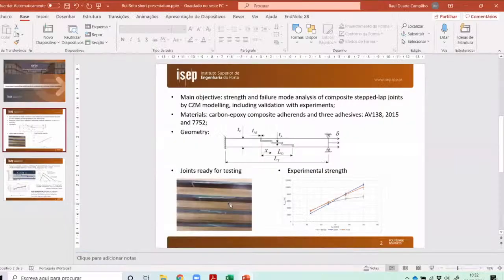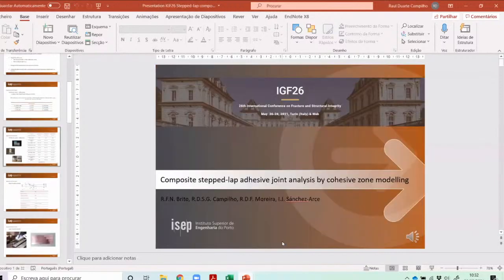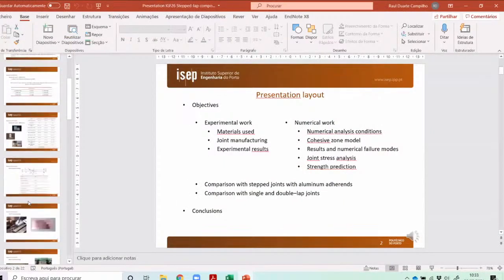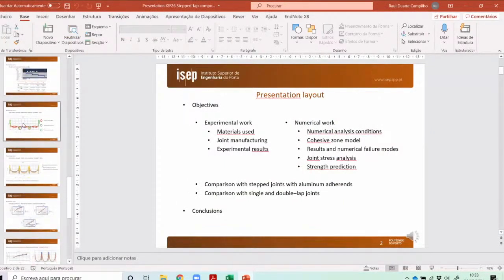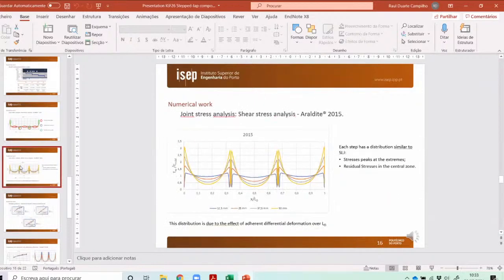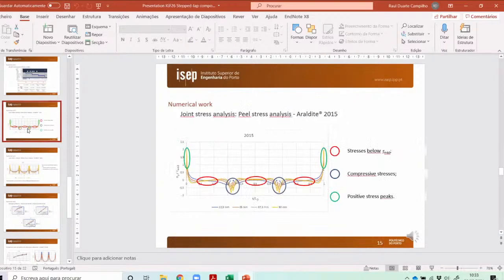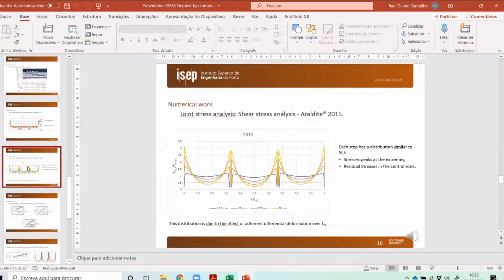Let me show you the full presentation because I have the stress distribution there. I have here the shear and peel stresses, but in this case I only have them for one adhesive. What happens with the stress distribution in these types of joints is that, for example, this plot is for the shear stresses, and we can clearly see the three different steps along this normalized length of the joint. And the peak stresses that we can see here are at the ends of each step of the joint.